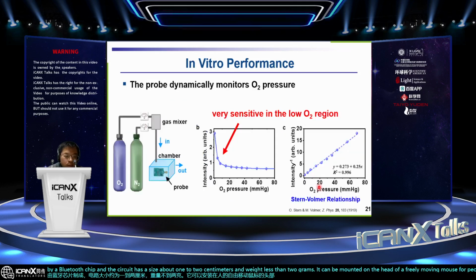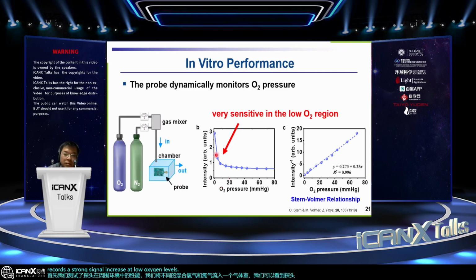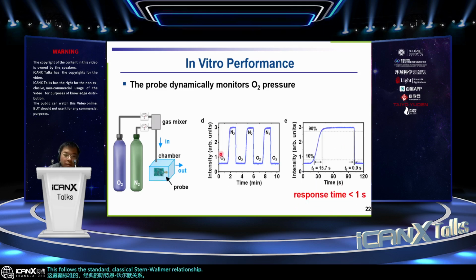First, we tested the probe performance in an ambient environment. We flowed different mixtures of oxygen and nitrogen into a gas chamber, and we can see the probe records a strong signal increase at low oxygen pressure. This indicates that this probe is very sensitive to low oxygen levels. And the inverse of the fluorescent intensity is proportional to the oxygen pressure. This follows the classical Stern-Volmer relationship. And here shows the dynamic response. We alternate the oxygen and nitrogen flows in the chamber, and we can observe the probe has a dynamic response to the gas environment, and the response time is less than 1 second.